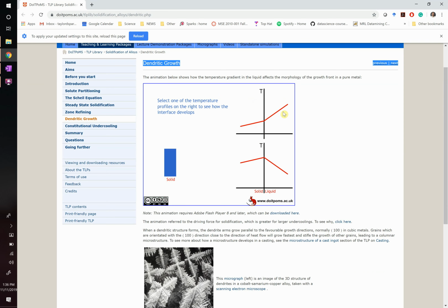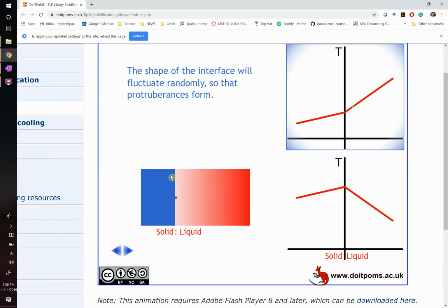In one case, the liquid is much hotter than the crucible, right? So you had a cold crucible, you poured your molten metal into it. Let's do that one first. So now you've got hot liquid, cold solid, okay? As you start to solidify, think about what happens. The first thing is that there's random temperature fluctuations, and at one spot it might be a little bit colder than the area around it. And so that little region is going to form a solid, and it's going to extend out into the liquid.